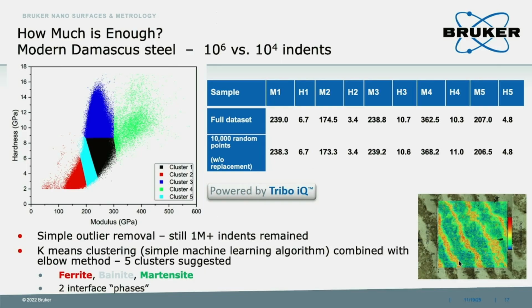So if we already know we have 3 different materials, one is the very hard martensite and the other one is the bainite phase. Of course, between different phases there is an interface, right? We cannot be sure, maybe some indentation locations are just at the interface. So we need to treat the interface as another different phase. So in total, we input 5 clusters, 3 from our different materials, 2 from the interface. So you can see the Tribo IQ running very well. It just helps us group the 1 million indents here. So phase 1, phase 2, phase 5. This is modulus, and H is hardness. So this is the value.